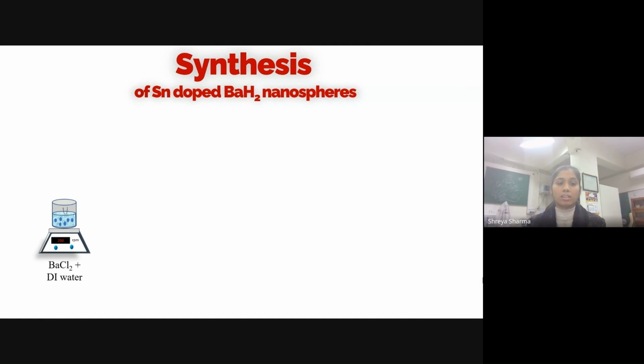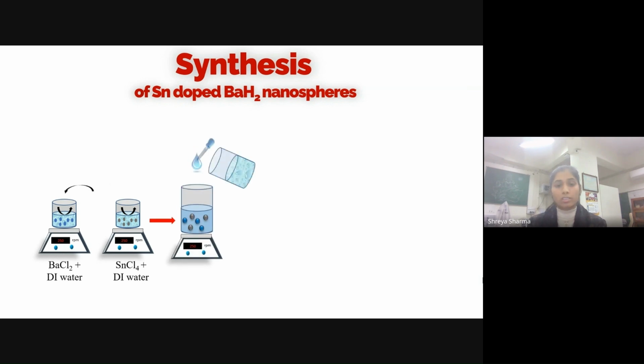Initially, we dissolved barium chloride into DI water and prepared the barium chloride solution. Simultaneously, tin chloride was dissolved by magnetic stirring in DI water, after which the latter solution was added dropwise into the former solution. The final solution was stirred for a few minutes, after which H2O2 was added into the mixture to change the reaction kinetics.